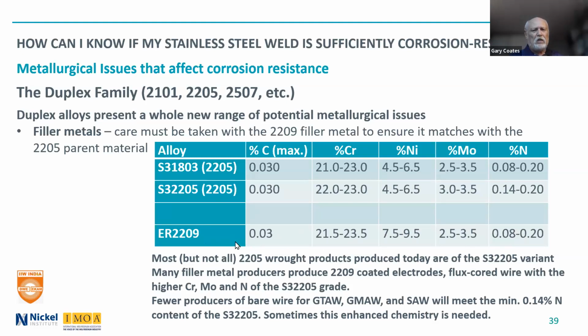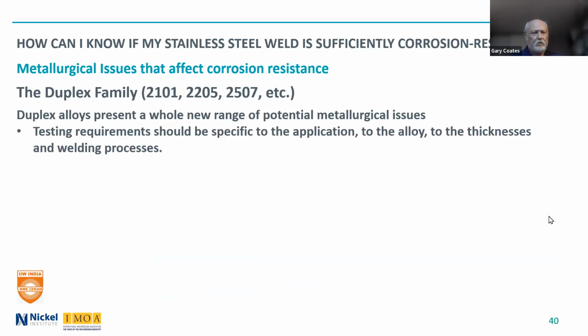And when it comes to bare wire, there are a number of producers that don't like the 0.14 minimum nitrogen content. It makes it very difficult to produce for them, higher defect in the wire production, and so therefore they resist it. So many times you can get away if it's 0.13, 0.12% nitrogen, but there are cases you may want to insist on the 0.14 minimum nitrogen in the bare wire.